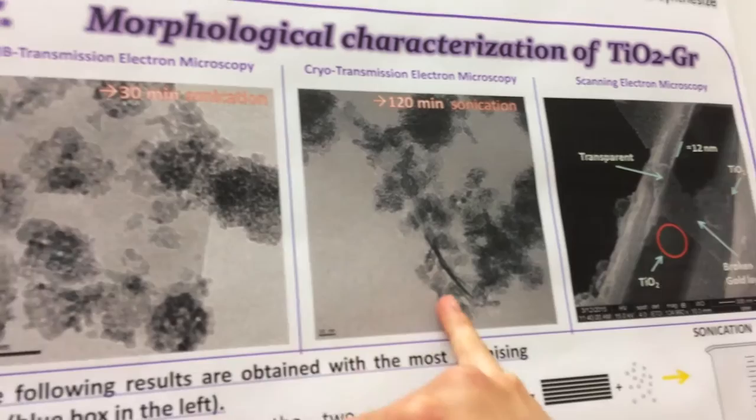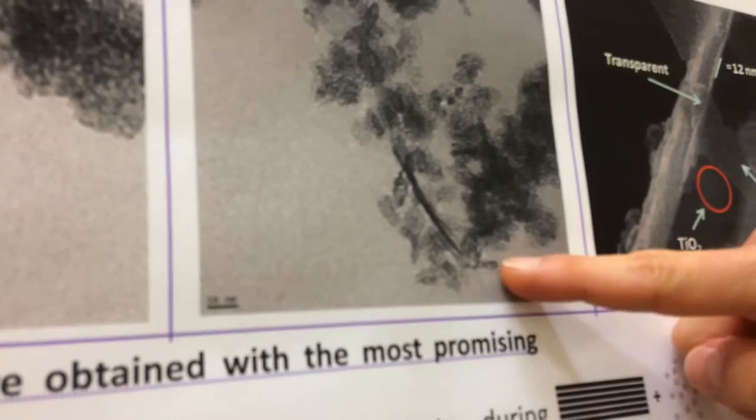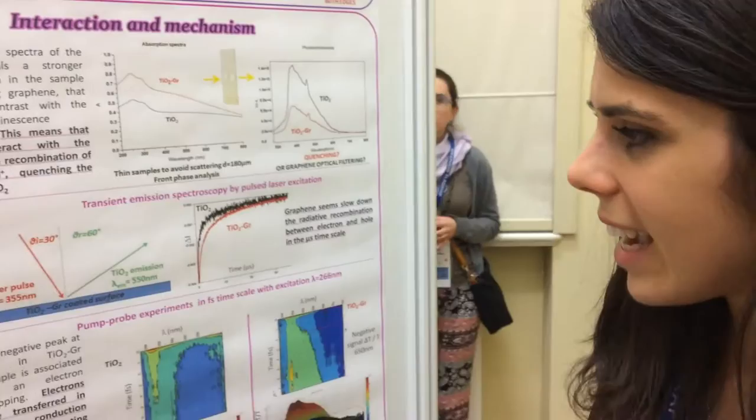Here you can see that titanium dioxide is going through the structure of graphite, provoking the exfoliation of graphene layers. This is a cryo-TEM image — here you can see graphite flakes perpendicular to the observation plane, and you can see that they are opening, so the titanium dioxide is intercalating inside the crystal lattice. We then move to characterization of the mechanism involving titanium dioxide and graphene.